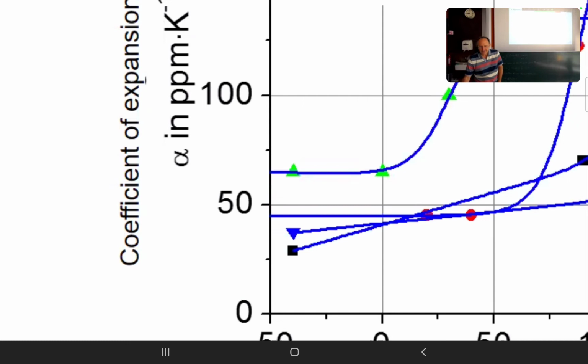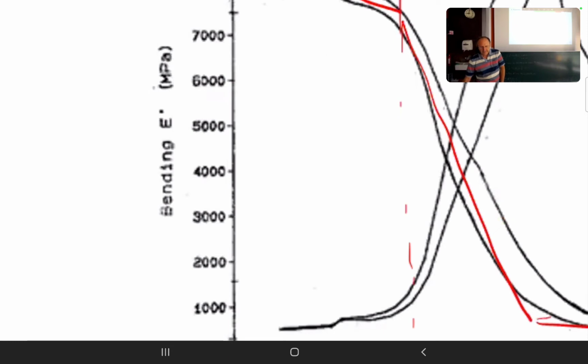As we can see, the polymer industry has many possibilities to control that behavior. So you could say by the chemistry of the epoxy, which kind of epoxy it is, you can determine where the glass transition temperature is. And by the amount of filler and also by the grain sizes of the filler, you can determine the properties at low temperatures and at high temperatures. So the more you fill in, the lower the CTE will be. At the same time, the Young's modulus goes down for such material, but it goes down, let's say, roughly by a factor of 10 when you go beyond glass transition temperature.